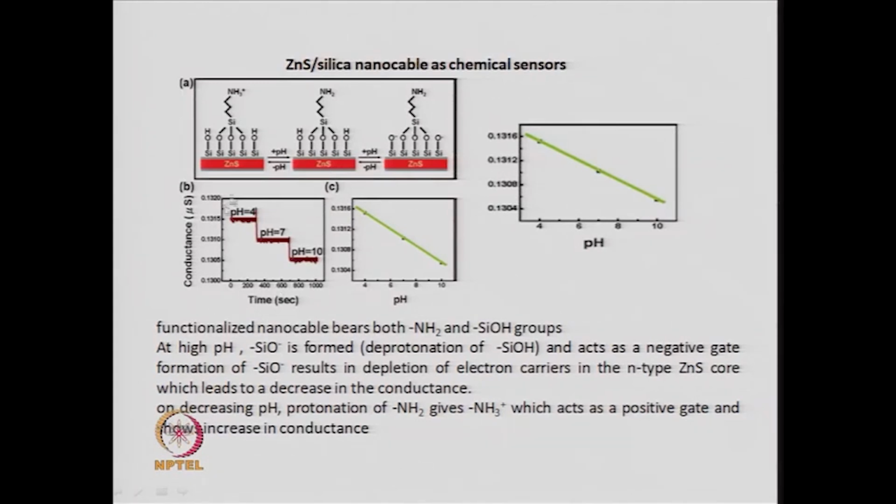When you are having this configuration, the conductance is somewhere here, some 0.13 microsiemens at around pH 4, and it is more or less constant.